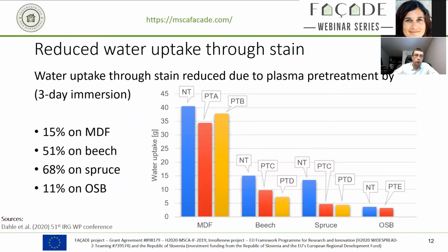And looking at the effects, there are all sorts of benefits that we can create from this. One to look into from the very beginning is reduced sensitivity to water, and to moisture in general. In this case, we plasma treated different wood-based materials with the industrial plasma jet, the gliding arc jet, like we saw in the pictures before. We had MDF, solid beech, spruce, and also OSB. In general, for different kinds of plasma treatments, we find a reduction of the water uptake through a water-based stain. So we had a plasma treatment, a water-based stain was applied, and after the stain dried and cured, samples were immersed in water for 3 days.